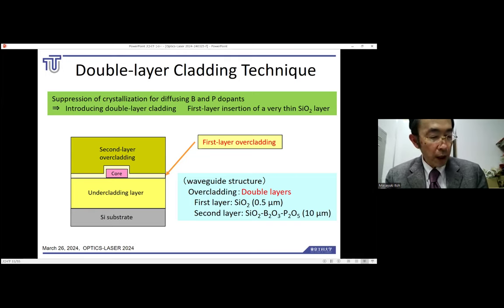The first layer is a very thin silicon dioxide film, 0.5 micrometer thick. The second layer has a double layer structure with a 10 micrometer thickness of ordinary BPSG. In other words, the first layer of silicon dioxide film prevents the diffusion of boron and phosphorus and avoids crystallization inside the core.